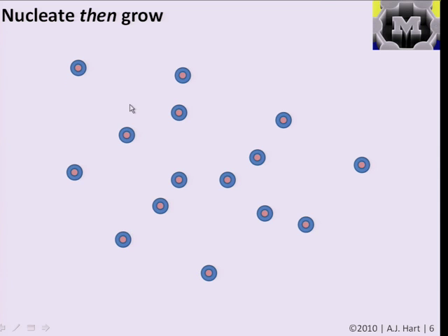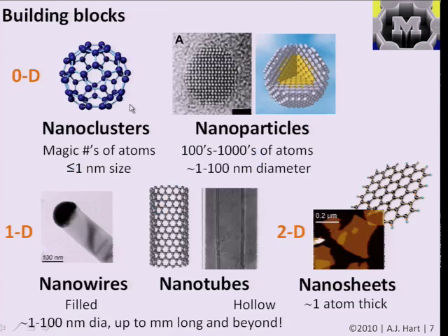And for example, in all cases, you're going to have a size distribution. You're never going to have everything exactly the same. But if, for example, larger particles grow at a slower rate, then that means that as time proceeds, the small ones will catch up to the big ones and your size distribution will focus. And that's exactly what is seen and confirmed theoretically and experimentally in the example that we are addressing.